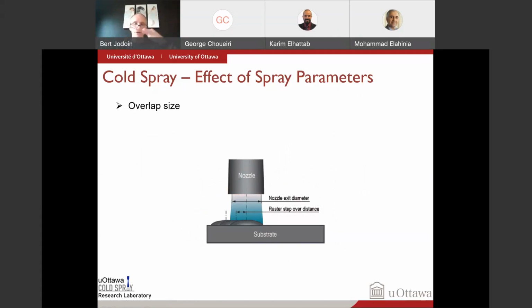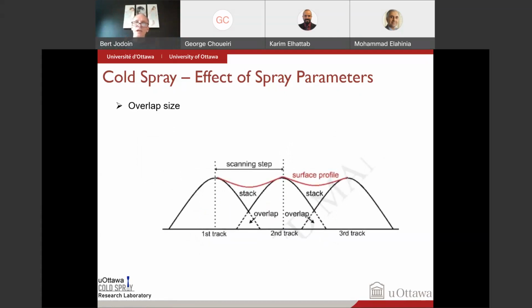Overlap size, of course, our coatings, they always have this little bump there. So depending on the way we spray, we try to make sure that we have an overlap to minimize the bump and the overall surface look like the red curve here, which could be a few microns or less than that.